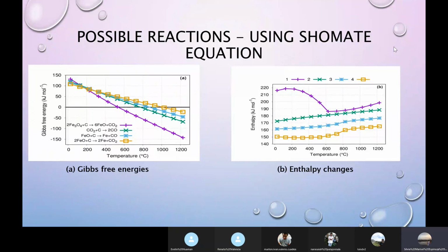In addition, all three reactions are endothermic, which explains the first endothermic peak of the DSC analysis. At this point we must assume that the three equations are carried out simultaneously, which generates a first peak of the DSC that is larger than the second peak. The possibility that these reactions occur simultaneously is reported in the literature.